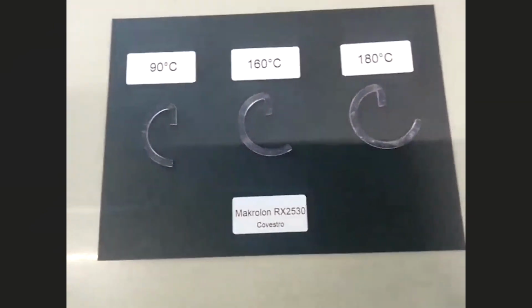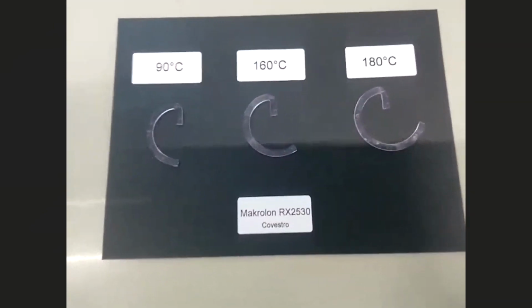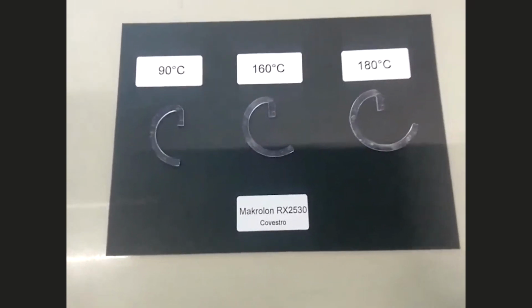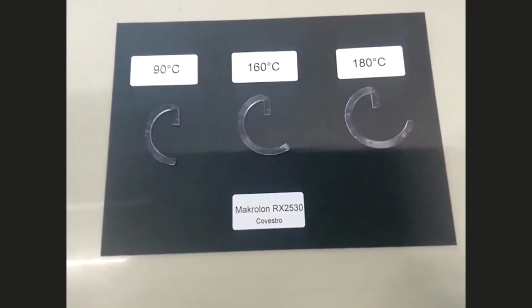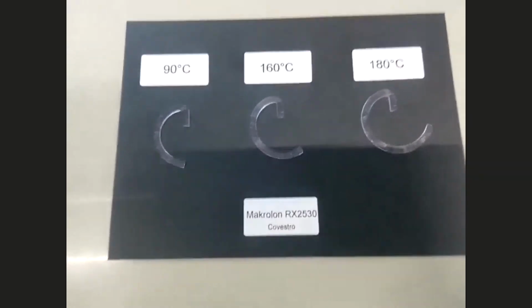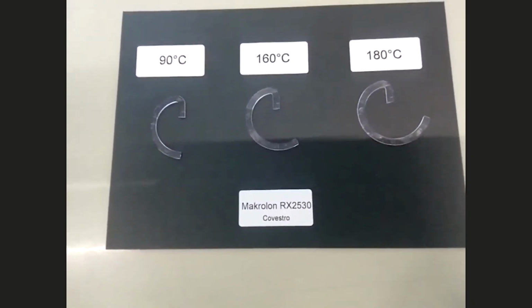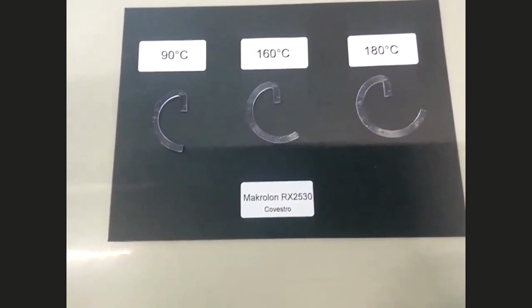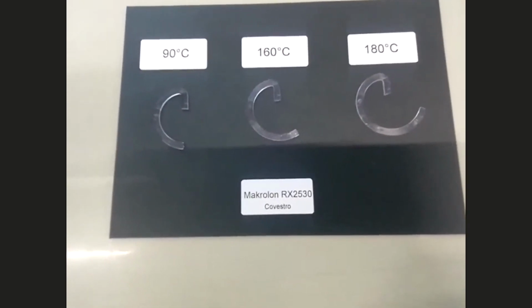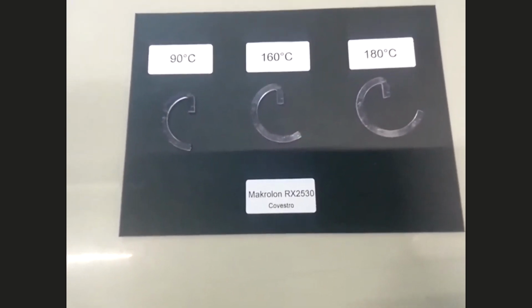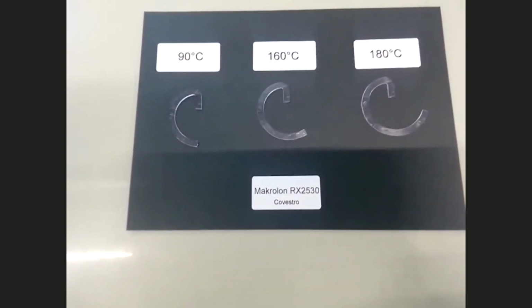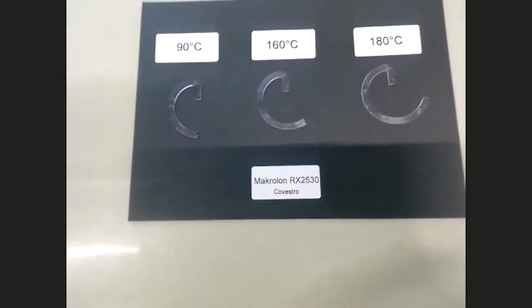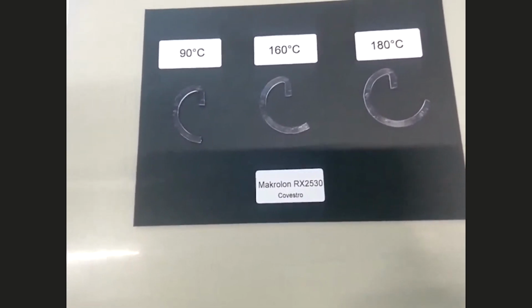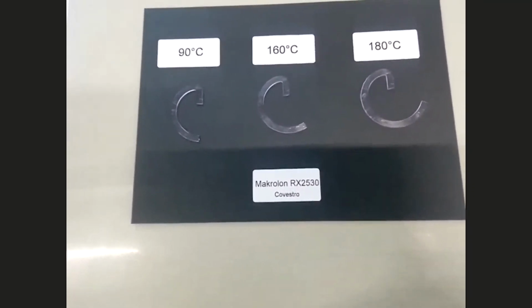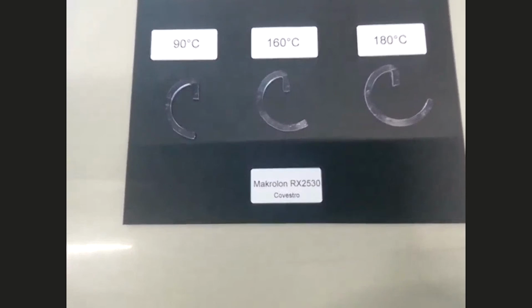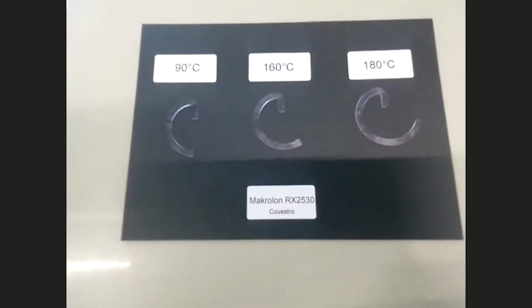So we inject during this live demo at 90 degrees in conventional mode and at 160 degrees with Roctool. But as Michael showed you, we also have an improvement of the flow if we increase 20 degrees, so at 180 degrees. To sum up, with Roctool you have the capability to improve the flow length, and depending on your application, you can choose which temperature is the best case for that.